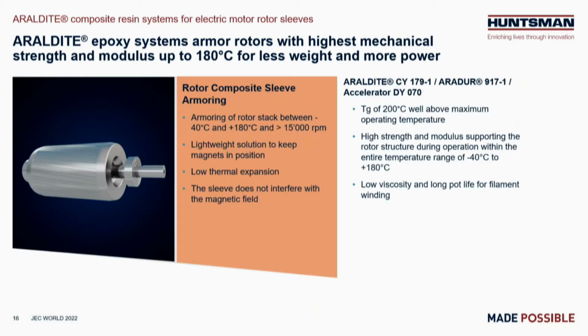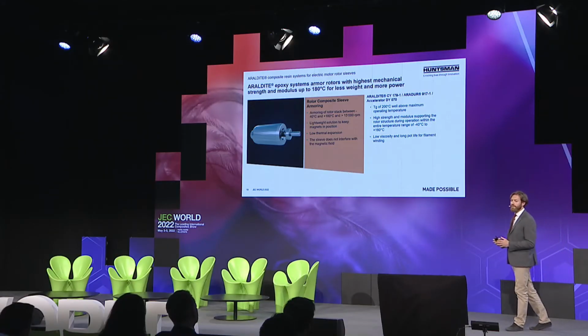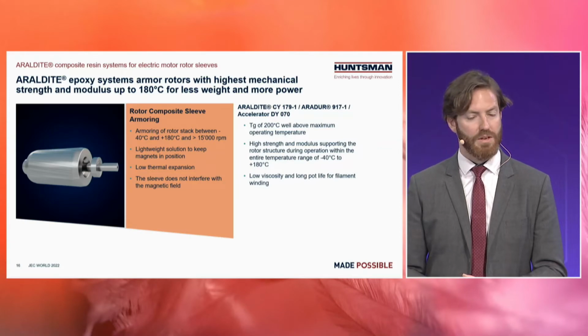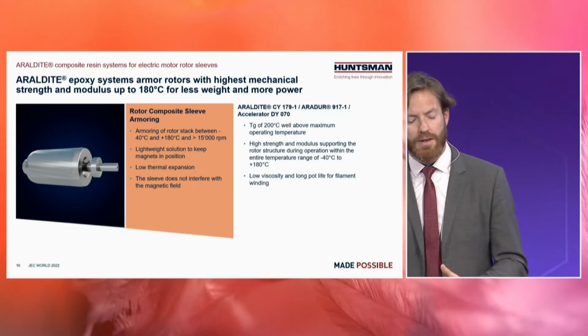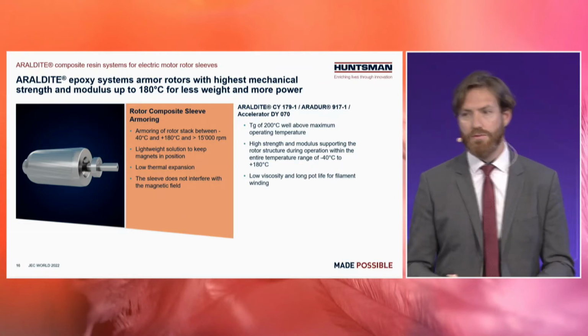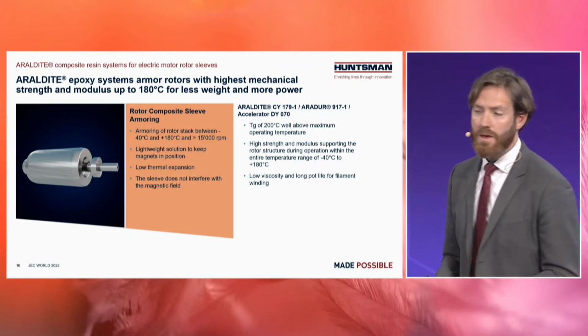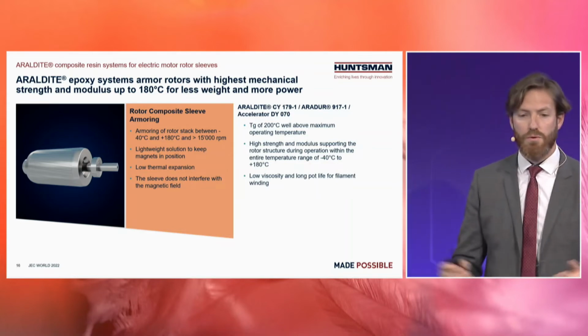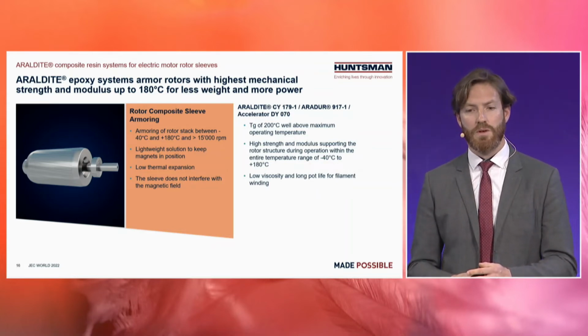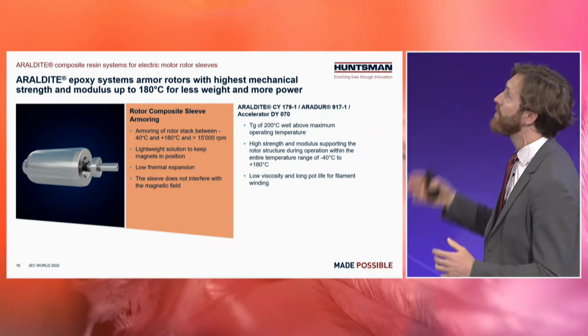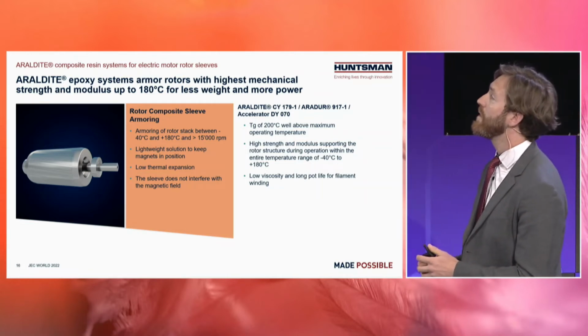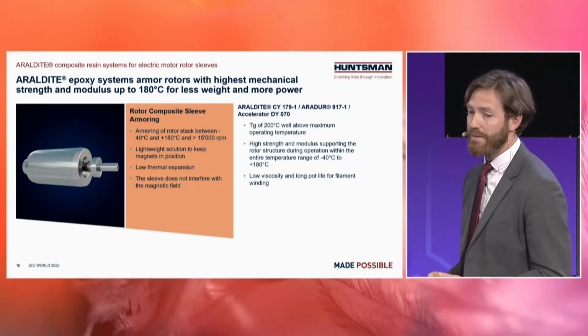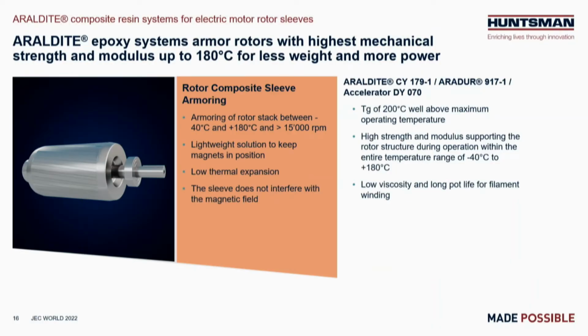So the second type of application is the rotor composite sleeves. The idea is to reinforce and maintain the structural integrity of the rotor during very high speed rotations, above 15,000 RPMs, in a temperature range from -40 to 180 Celsius. So we have a system dedicated to wet filament winding with a low viscosity and a high thermal resistance up to 180 Celsius.